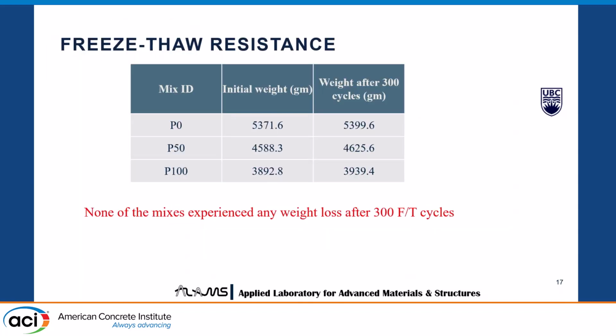And if you look at the freeze thaw durability, we actually checked the mass after 300 freeze thaw cycles. We can see that none of the samples had any weight loss after 300 cycles. So we can say that P100 with 100% poraver performed as good as the control concrete in terms of freeze thaw durability.